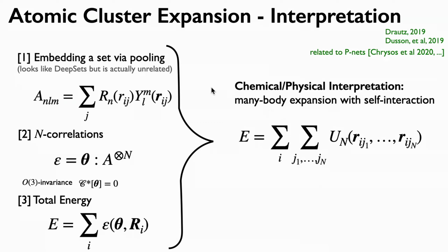The next thing to observe here is the cost. You get linear scaling in the total number of atoms because of the spatial decomposition of the total energy. You get linear scaling in the atomic environment size, so if I have 30 or 100 atoms, the cost of assembling this grows linearly. And then you have whatever scaling comes out of the cost of this tensor product.